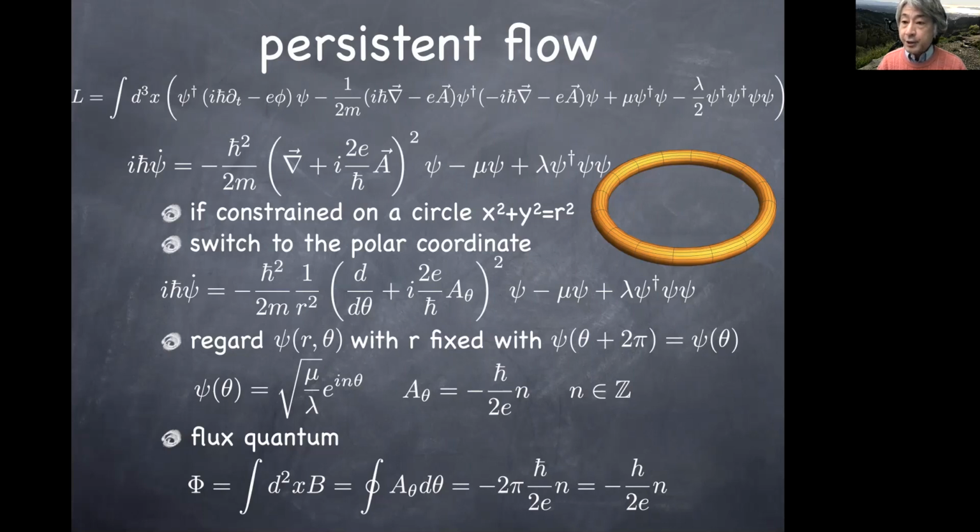But now you can actually test this experimentally, namely that if you measure the magnetic flux going through the hole inside this tube, and if you verify that it is indeed quantized in the unit of h/2e instead of h/e, that is an experimental evidence that the condensate is really made up of pairs of electrons, not electrons singly. And indeed, the data do show that.